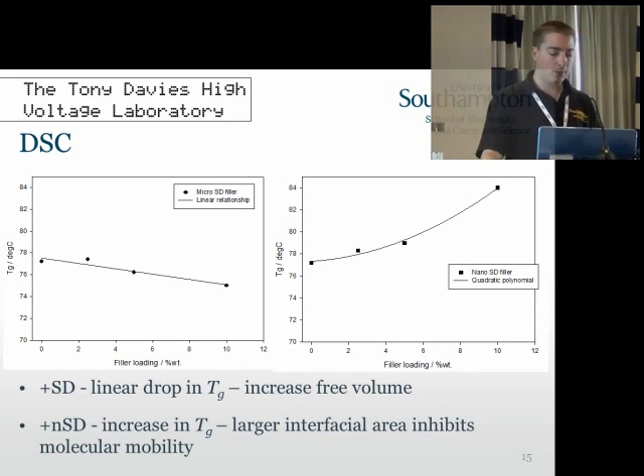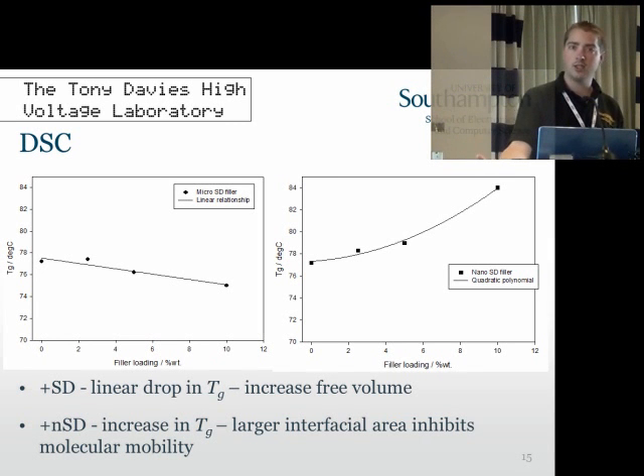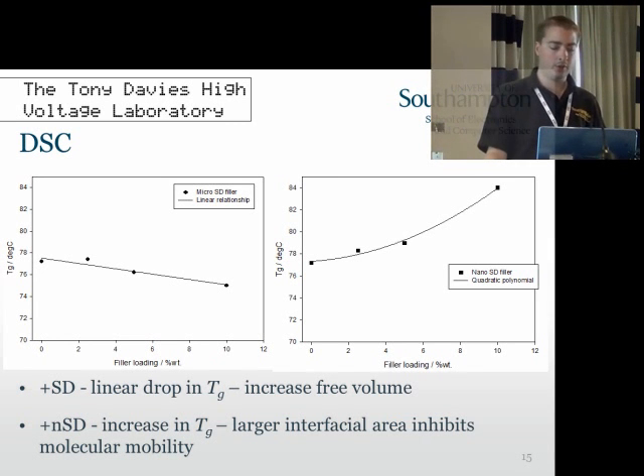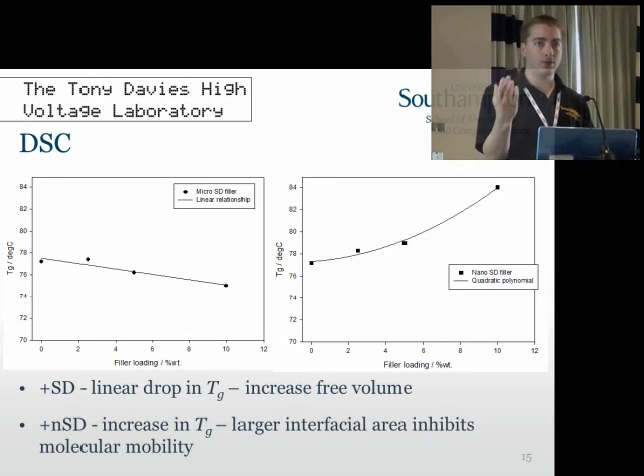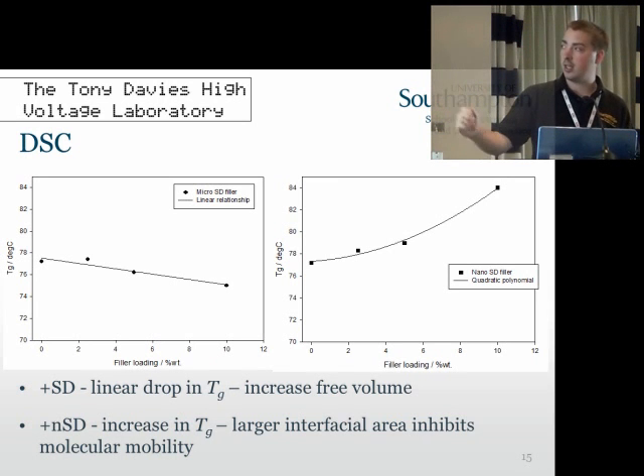However, on the right figure, when we add the nano-filled system, as we increase the filler loading, we see a large increase in the TG. Now, this is likely due to the larger interfacial area, as mentioned in the previous talk. When you have such a nano system, the interaction between the matrix and the fill are going to be a lot more significant. And obviously, in this case, it inhibits the molecular mobility within the system.